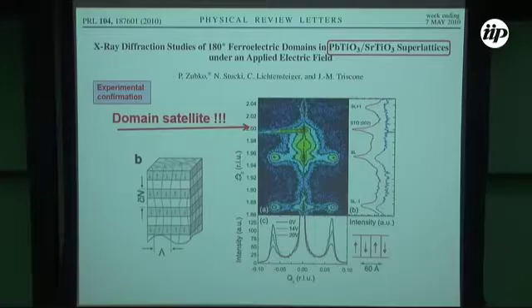Actually, the experimental proof of the existence of ferroelectricity with domains was done by Pavlo Zubko. He was working at the time in the group of Triscone, with his collaborators. First of all, it's not easy experimentally to show the ferroelectric domains because they have no influence on optics. They are not very well coupled with elasticity. So experimentally, this is a challenge to demonstrate. What he did, he just demonstrated that the usual Bragg peaks have some satellites. So he demonstrated the existence of the superstructure, which he associated with the domain structure.